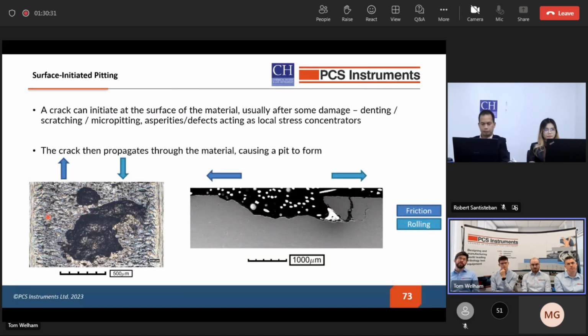So this crack will propagate, it will go deep into the surface, and then it may at some point return back up to the surface or interact with another crack, and you get a large chunk of material parting off and creating this large crater, this pit.